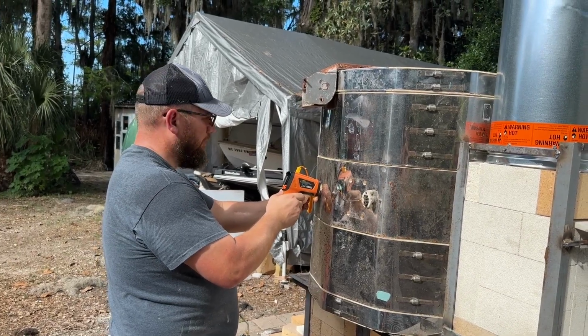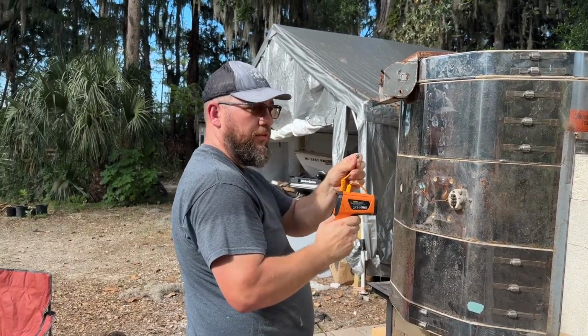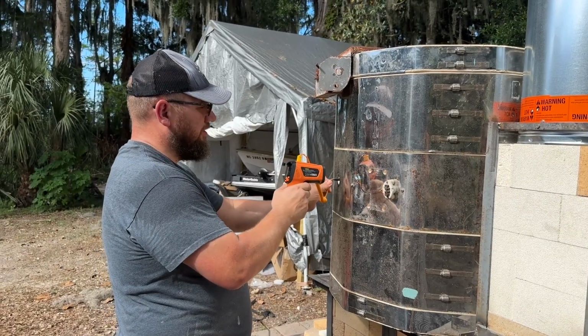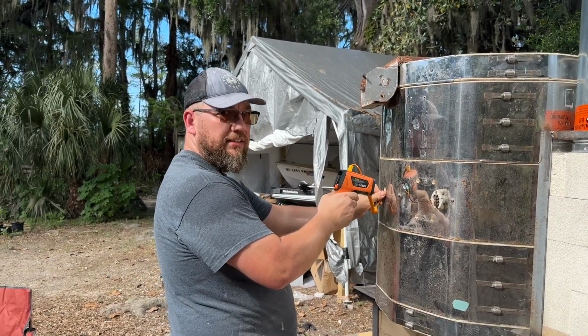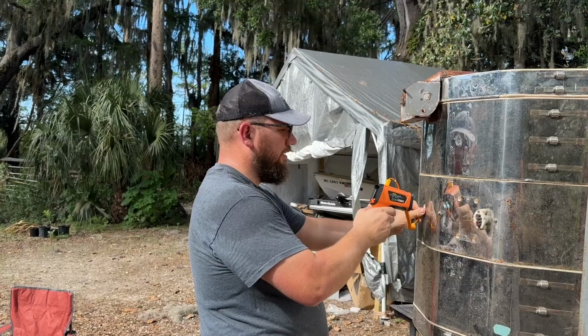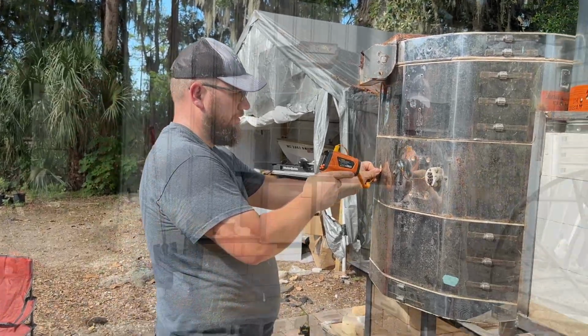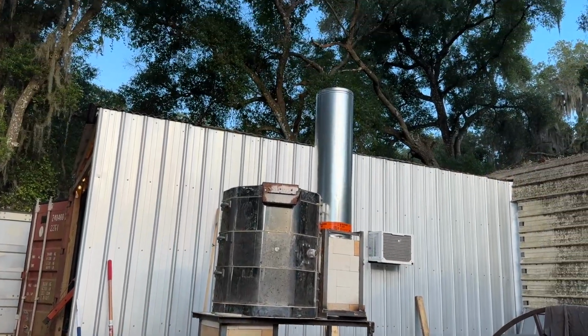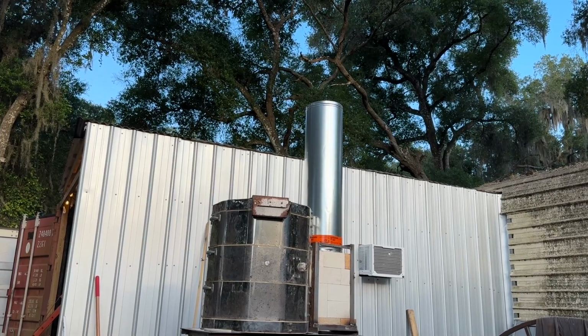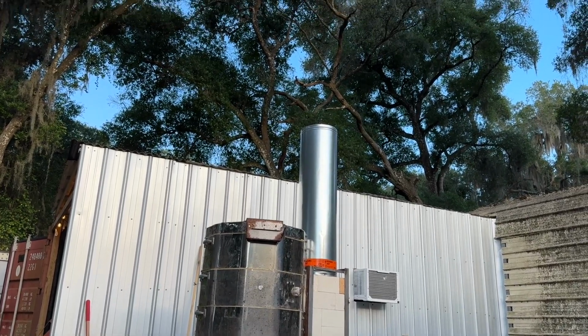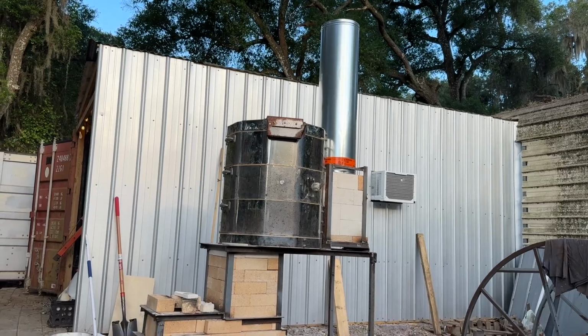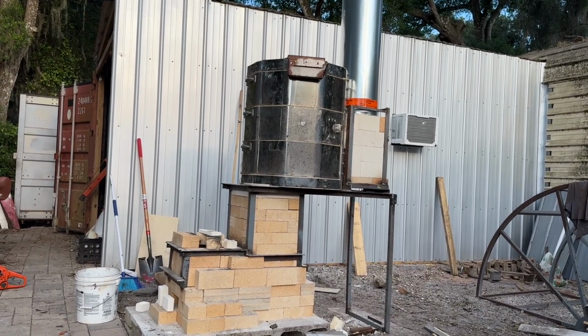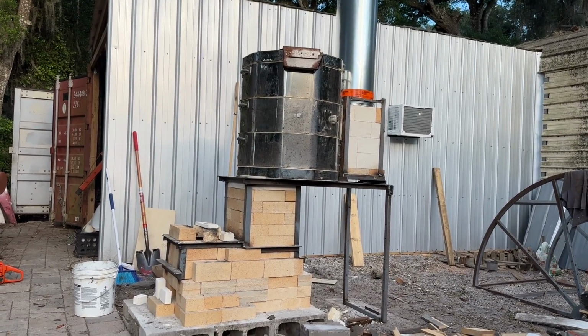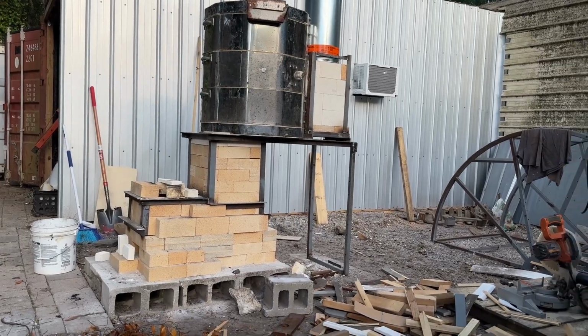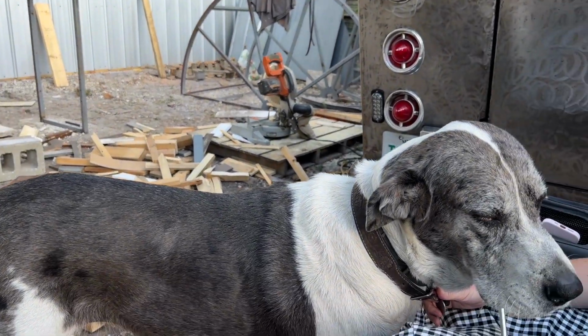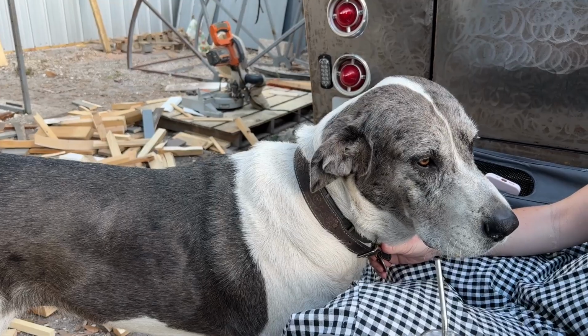So I have a thermal imaging gun with the probe measuring the temperature. I want to keep this under 200 degrees for 2 hours to dry out the ware. All right, we're at about 650. Running charcoal in this bisque fire. There's no smoke, you can see heat coming out, but smokeless. It's climbing just on schedule on the template that they gave on the wood-fired kiln site. And we got the safety manager here making sure everyone's safe.